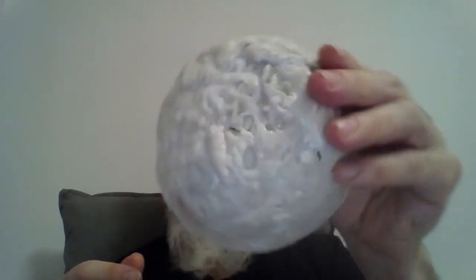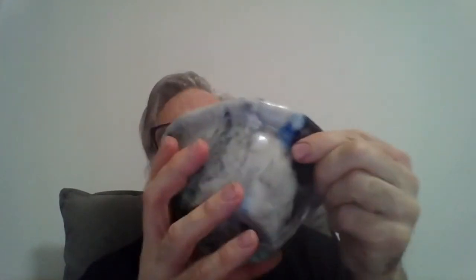we looked at bowls. We just wanted to do a basic bowl form, but what we found was that if you used the material and didn't use the right amount of pressure, you may end up with something like this. You may end up with something that looks very much like spaghetti stuck together. Or you may end up with something like this, where we got the temperature right, so it's nice and glossy on the outside, but then we had too much surplus material around it.